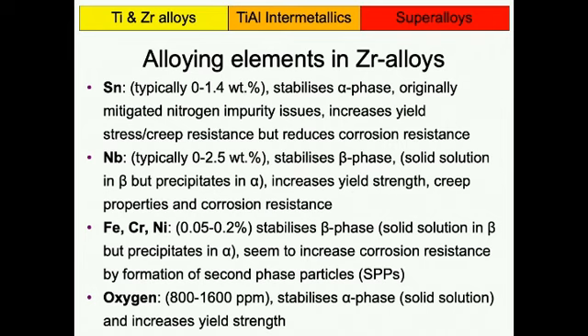So it doesn't have much solubility in alpha phase, but it's a very sluggish alloying element. So the confusion probably comes from the fact that you might retain quite a bit of niobium in the alpha phase if you don't heat treat your material long enough. So it can be retained in the alpha phase in a metastable way. It increases the yield strength. It also seems to help the creep properties, and it seems to help the corrosion resistance. But in what way, we don't really know. Well, there are some ideas, but it's still not very well established.